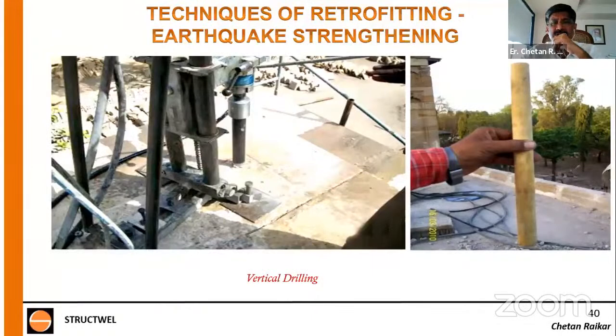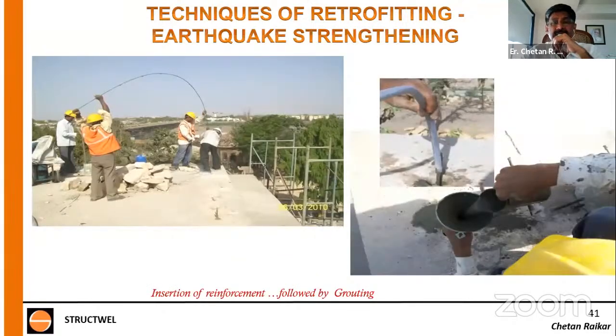This is how the drilling was done, using a simple coring drill. Of course, little modifications had to be done to that, but we were able to take out piece by piece, stone by stone. We were able to bring it out, and through cores were formed. This is how the steel rod was inserted. And what you see in the left photograph is the whole area is grouted with 10 mm down, flowable concrete using high range water reducers. So a simple technique with which we were able to make the load bearing masonry into a reinforced load bearing masonry, which gives resilience to the structure now, and the reinforcement is not seen anywhere.